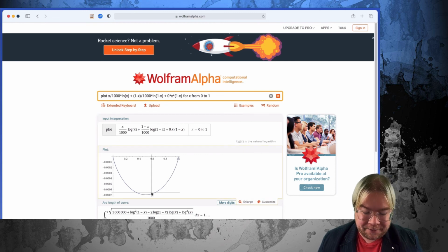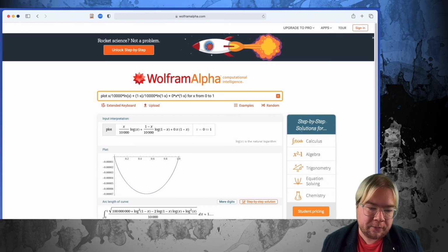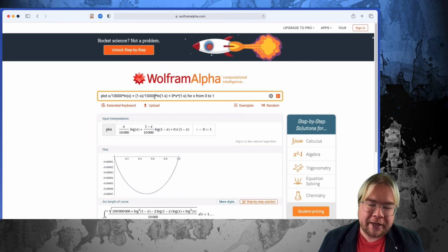And it doesn't take much to, let's just say we increase the degree of polymerization by a factor of 10. And this is certainly possible with really high molecular weight polymers. You see I've decreased it even more. So I'm quickly approaching 0. So entropy doesn't really help me mix polymers. Let's go back to this case.